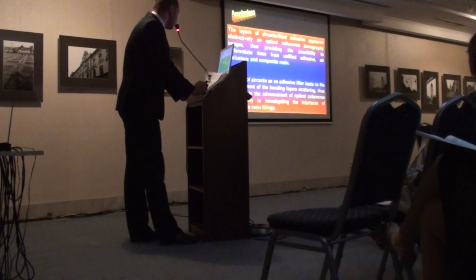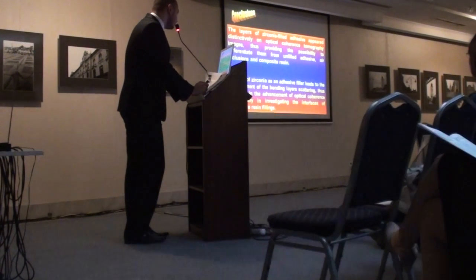In conclusion, the layers of zirconia filled adhesive appear distinctively on optical coherence tomography images, thus providing the possibility to differentiate them from unfilled adhesive, air inclusions, and composite resin. The use of zirconia as an adhesive filler leads to the improvement of bonding layer scattering, thus resulting in an advancement of optical coherence tomography investigating the interfaces of composite resin fillings. Thank you very much.